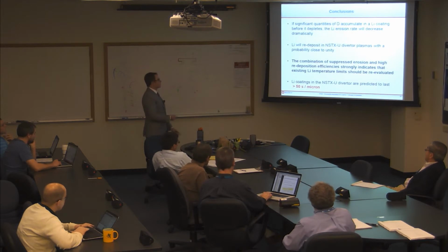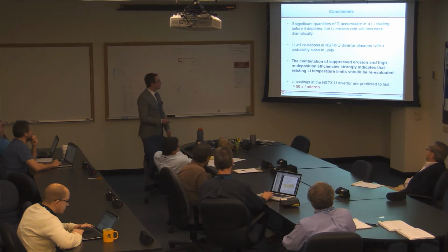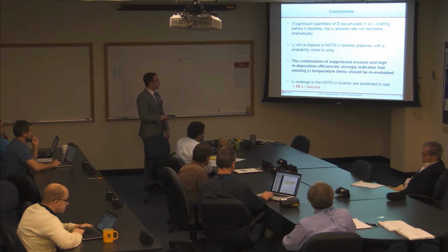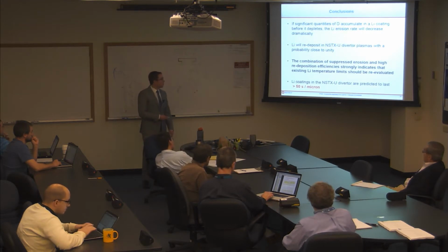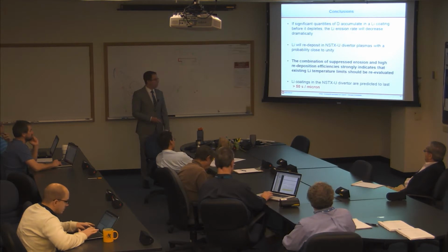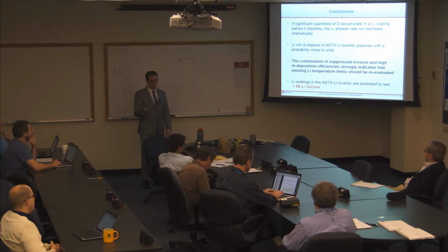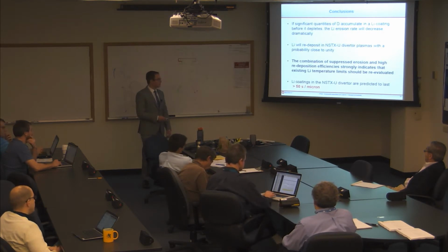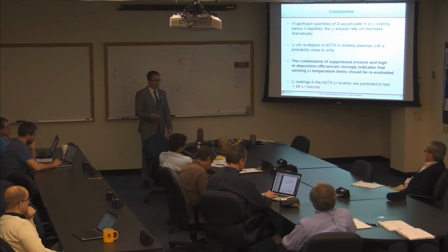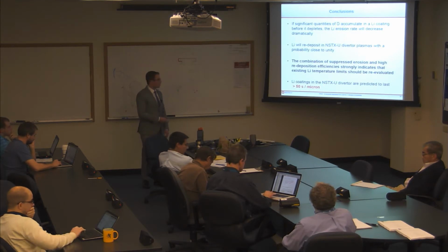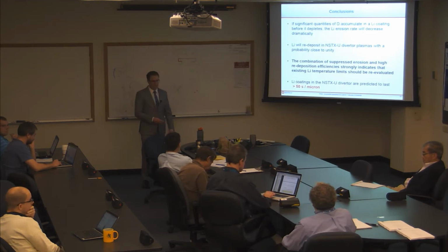Okay, conclusions. If significant quantities of deuterium accumulate in a lithium coating before it depletes, the lithium erosion rate will decrease dramatically. Lithium will redeposit in NSTX-U divertor plasmas with a probability close to unity, and the combination of the suppressed erosion and the very high redeposition efficiency strongly indicates that existing lithium temperature limits on this high-Z substrate should be reevaluated. And I predict that the lithium coatings in the NSTX-U divertor, in that density and temperature range that I showed you, are predicted to last 50 seconds per micron.